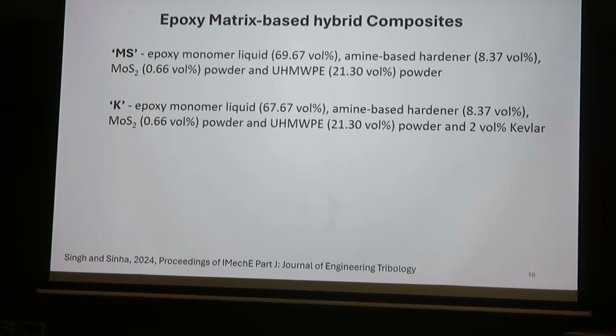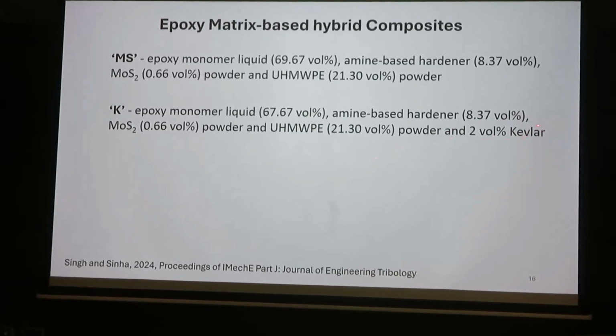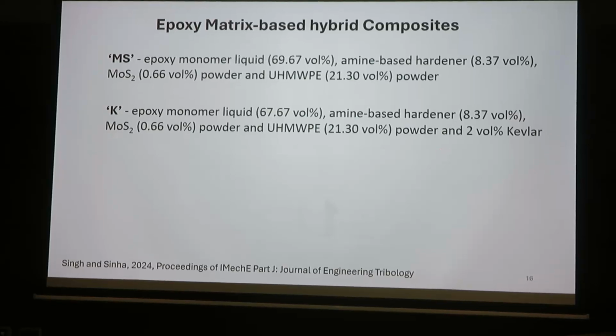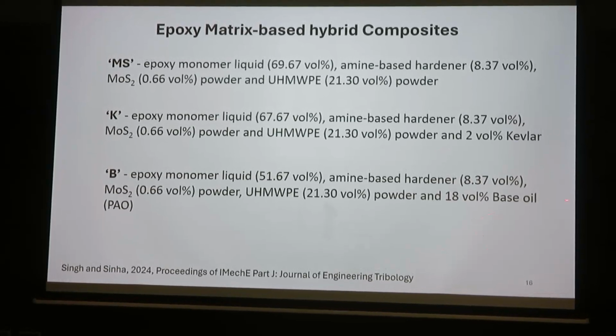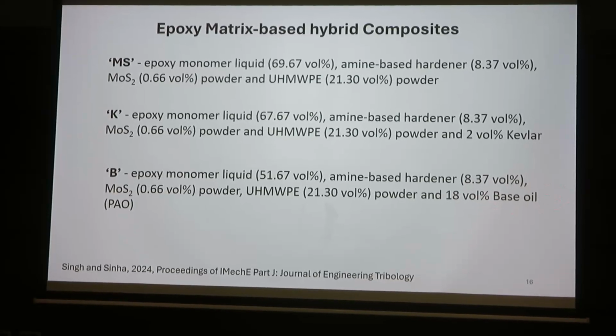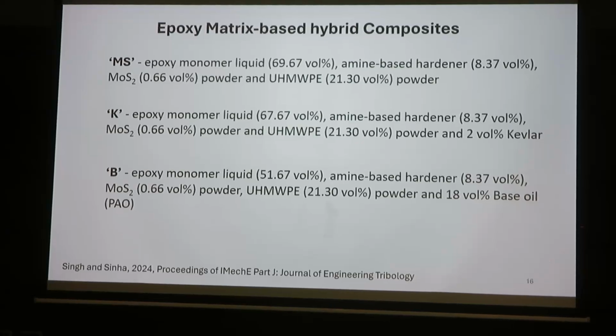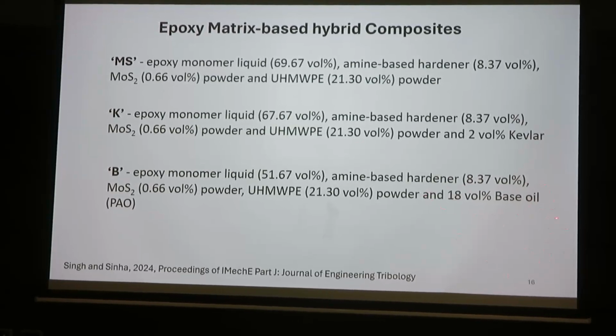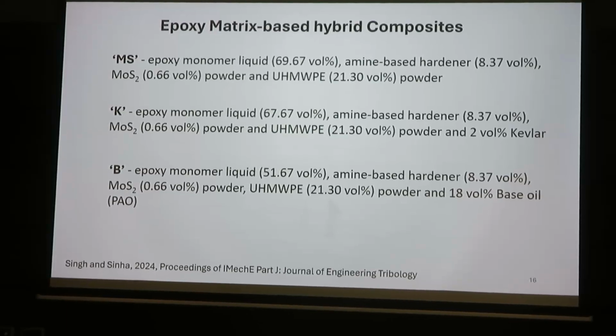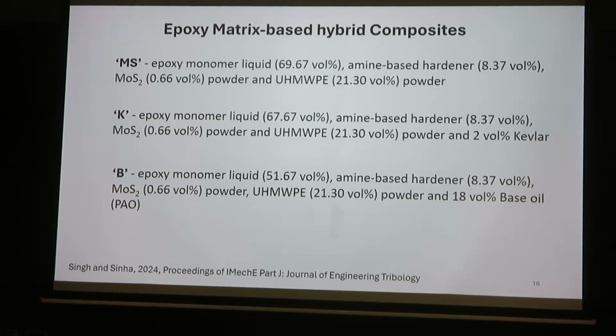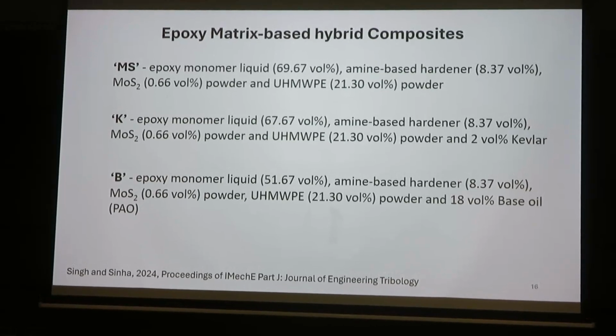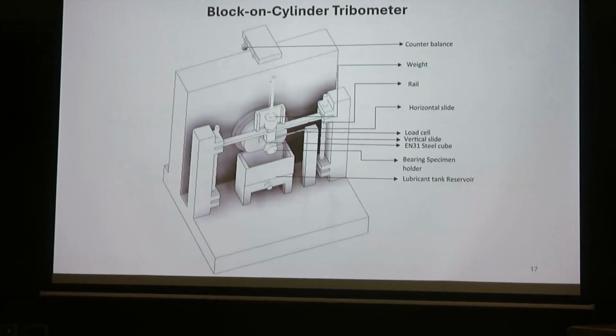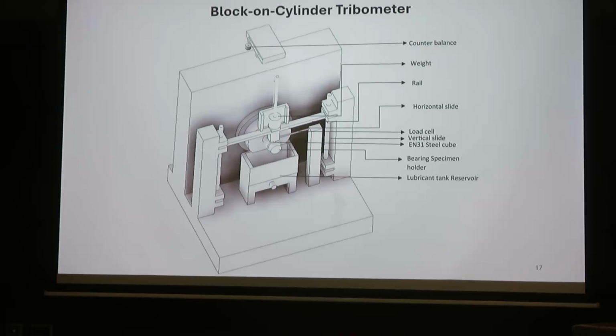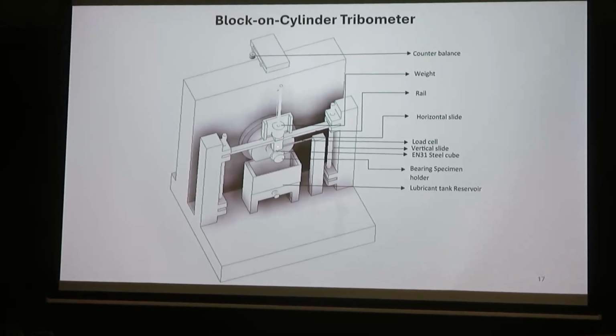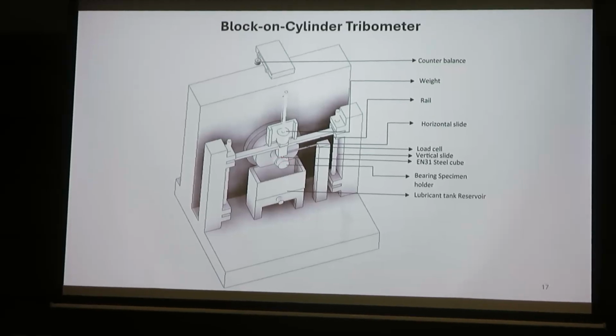Then some other ideas we have tried. For example, adding 2 weight volume percentage of Kevlar fiber in it. And another idea is where you can use liquid lubricant as a filler. So here the filler inside is liquid lubricant, so that gives us a continuous supply of lubricant at the interface. So it is still dry, but with some amount of oiliness at the interface. So these 3 composites we have tested, and the tests were conducted on a block on cylinder tribometer, so something like this. Here there is a block and there is a cylinder here. So the cylinder is rotating and the block is sitting on top of it.